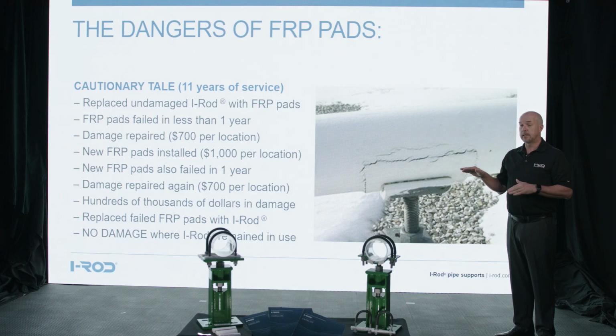For some reason, I don't know exactly why, they decided to remove many, not all, of the flat supports with the 2 bolts and install a curved saddle similar to this one here in the front, as you see in the image, with fiberglass FRP wear pads. So they installed these on several or many or most of the pipe supports, and after 1 year, those fiberglass wear pads separated, moisture got in, they started to see corrosion issues. Cost them approximately $700 per location to repair that.